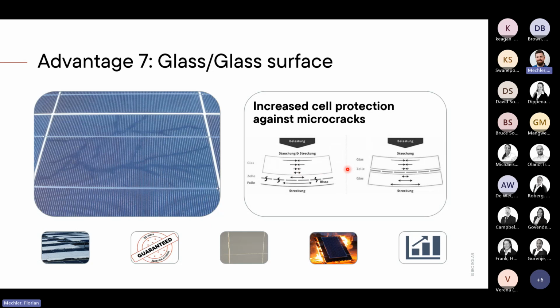When you have a glass module with the same glass thicknesses on the front side and on the back side, it's now this picture here. You have some stresses on the front side, you have some stresses on the back side, but the cell is in a neutral zone in the middle. So you avoid micro cracks in the cell because there are no stresses in this zone. So it's better for the cells to have a glass surface.